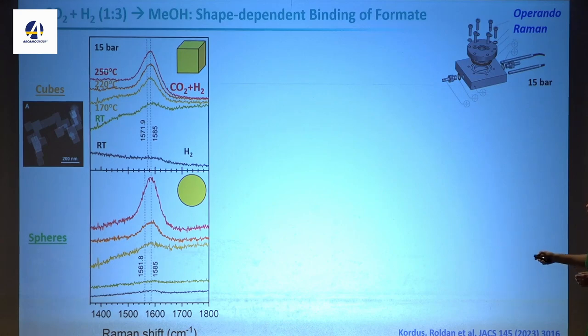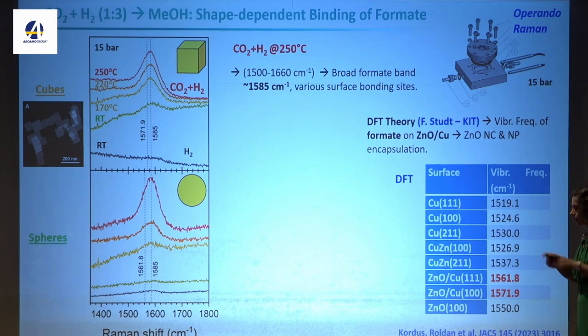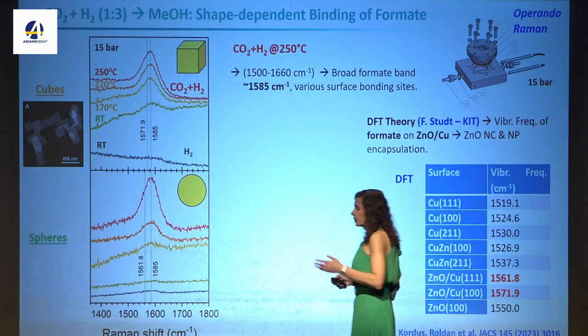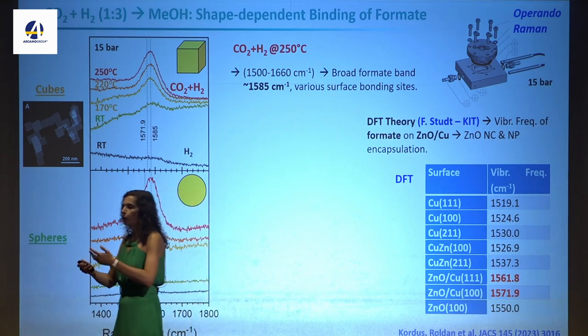So I show you some of the bulk-sensitive techniques, but I wanted to bring also, copper is a very good material to do a spectroscopy with Raman, because it has a very good surface-enhanced Raman signal. So in this case, we developed a Raman cell that can work under 15 bar, so we can get closer to the reaction conditions. And we look at these samples, the cubes and the spherical precatalyst, under reaction conditions, and we start monitoring the formation of formate. These are the formate bands. And we get from these Raman shifts certain values, and we're talking to the theorists and telling them what this corresponds to.